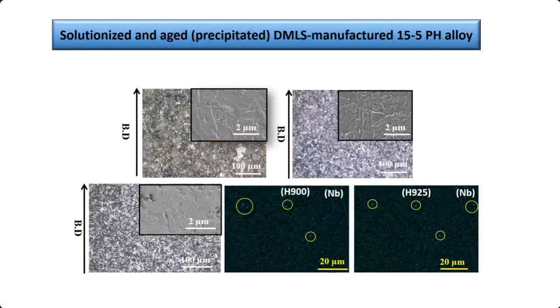What we did in this case is, apart from the as-built one, we also heat treated it with the conventional aging treatment used for this precipitation hardened alloy, because unless we do this kind of aging treatment, we are not able to get the full benefit of the precipitation hardening.